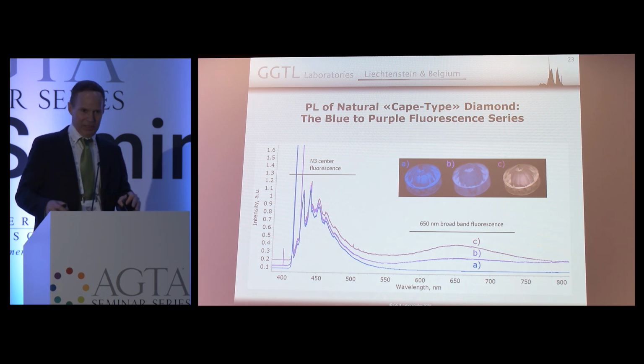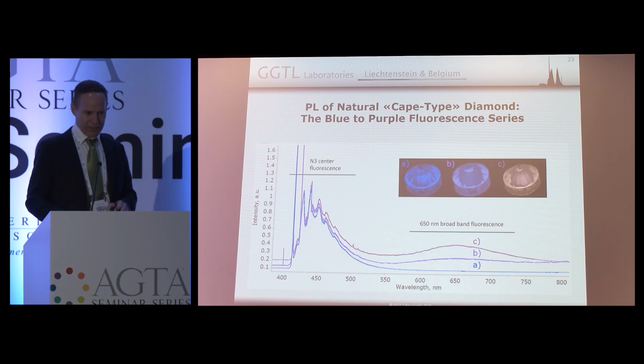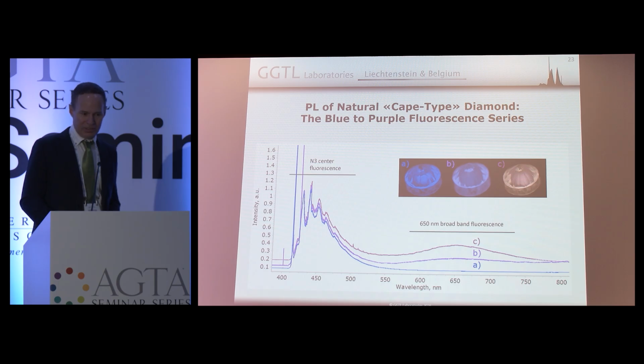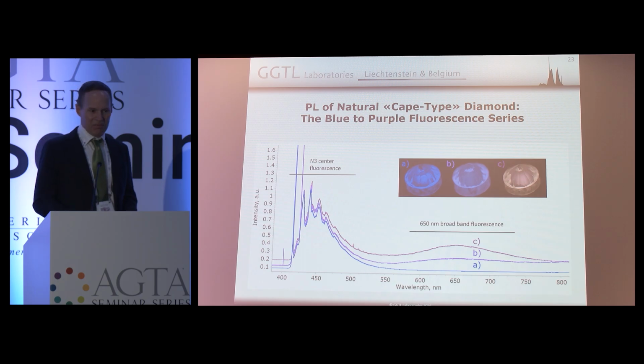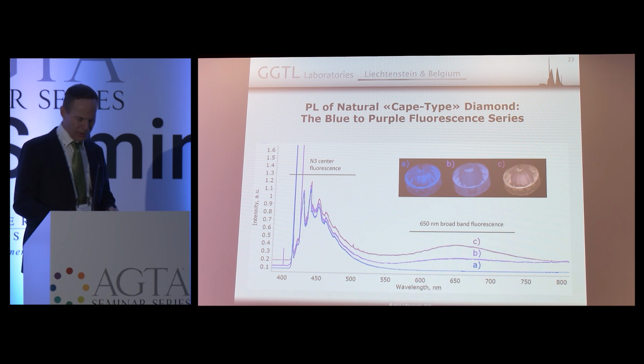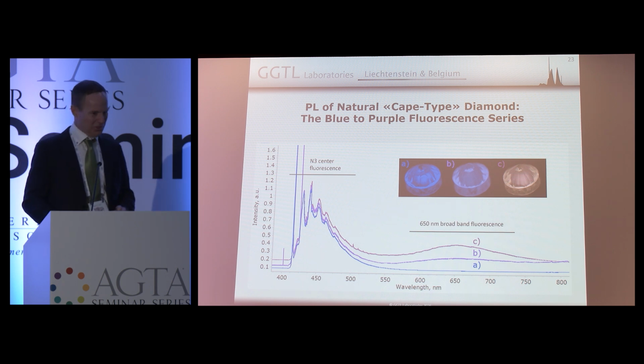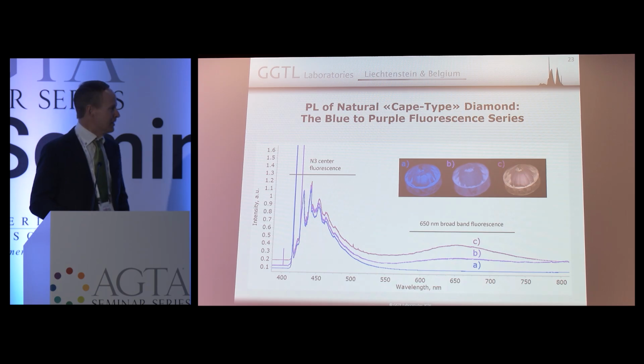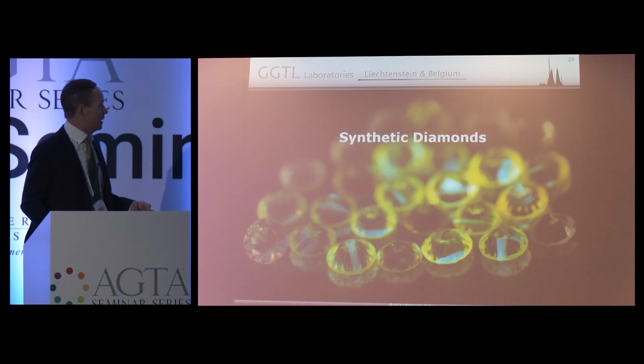So I can even tell you right here, before we even get to the segment of synthetic diamonds, if you have a diamond that fluoresces distinctly any color, doesn't matter what color, under long wave, then so far, at this time, you can be almost 100% sure that your stone is natural. Because synthetic diamonds, when they are excited at long wave, no matter if CVD or HPHT, they never fluoresce strong when they're colorless. Again, limited to colorless, not colored diamonds. But for colored diamonds, that's a good clue. If you have a strong blue fluorescing stone, oh, you're fine. You don't even have to go and test it, at least until at this time.